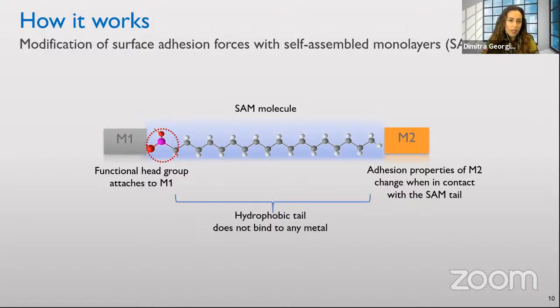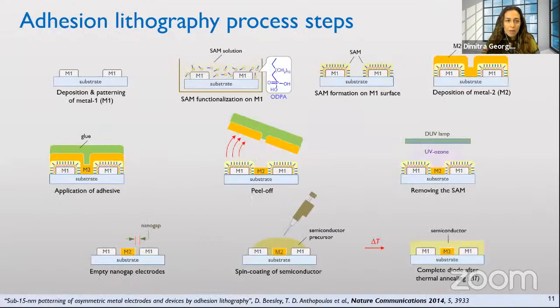However, this hydrophobicity induced on top of this metal changes the adhesion properties of a second metal when we deposit it on top of this SAM functionalized first metal. And I will explain right now how we take advantage of this property to fabricate our nanogaps. The steps of the adhesion lithography process are quite simple. We start by depositing and patterning the first metal with standard photolithography according to the shape that we choose. And then we dip the patterned substrates in the solution of this molecule I showed before.